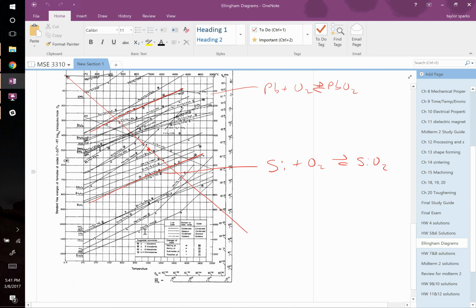This one down here at the way bottom, that's calcium picking up oxygen to form calcium oxide. How favorable is that? Massively favorable. Down here, magnesium picking up oxygen to form magnesium oxide, same thing. Lithium forming lithium oxide. These things happen, they're way low energy. And the way to think of it is like, this is a free energy scale. It's becoming supremely negative down here, right? And this corresponds to the reaction as written.